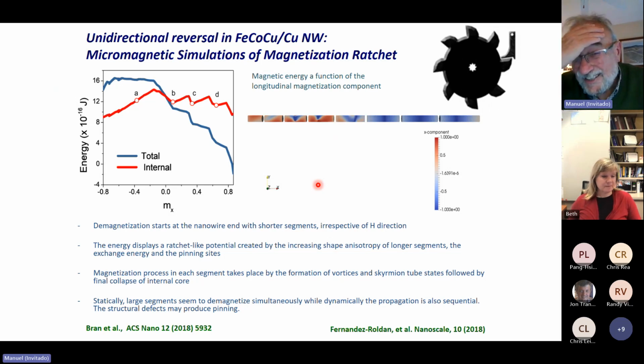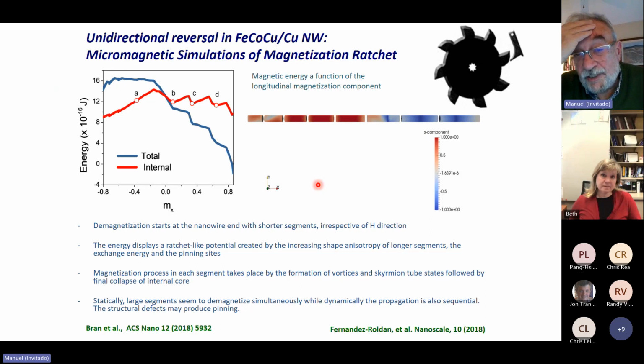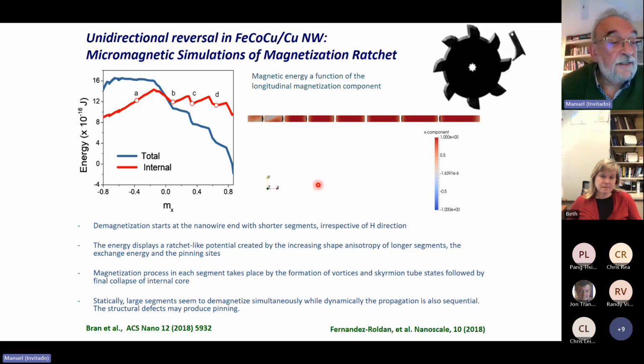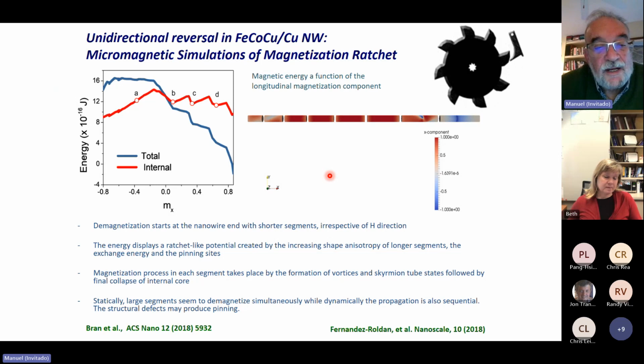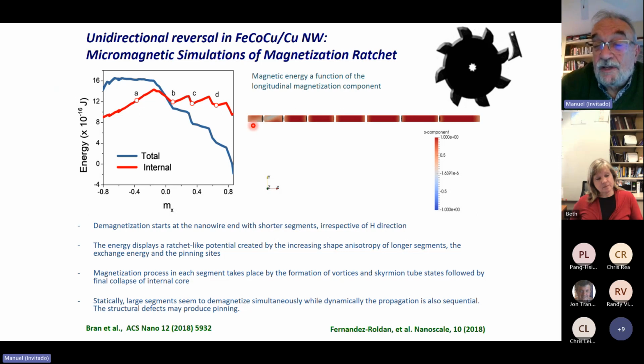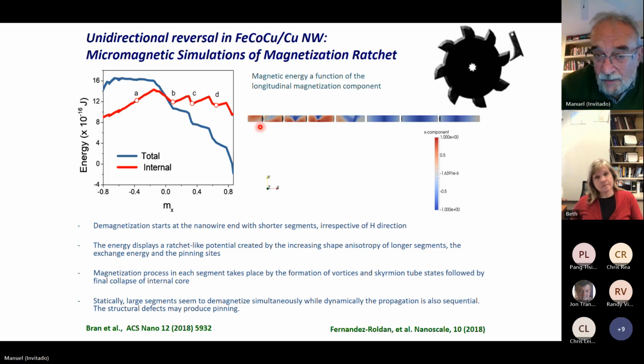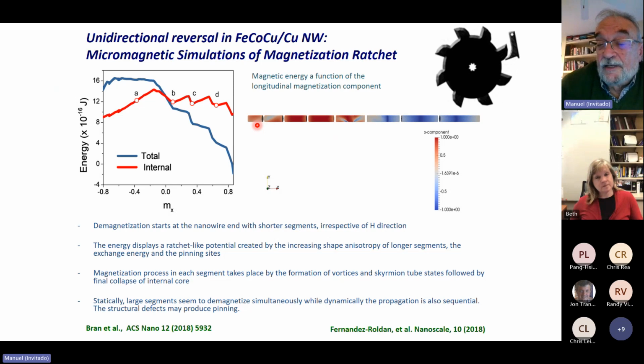Actually, the origin of this unidirectional reversal can be determined. According to these simulations, we think it is determined by the demagnetization process of the segments. The segments to the left, which are smaller in length, have a larger demagnetizing effect. So it is expected that these segments reverse magnetization at a smaller field, and then this reversal propagates along the entire length of the nanowires.